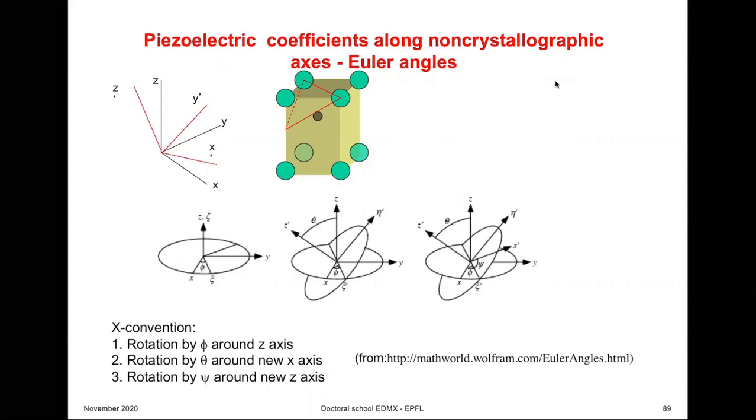It turns out that this is of very great practical importance. We find that the most performant crystals, relaxors or ferroelectrics, have the largest piezoelectric coefficient not along the polarization, but along some other direction. And for quartz, for example, for timekeeping, the most stable piezoelectric property, such as resonance, is observed along directions that are not among the principal crystallographic directions. This is the job in front of us in this section.